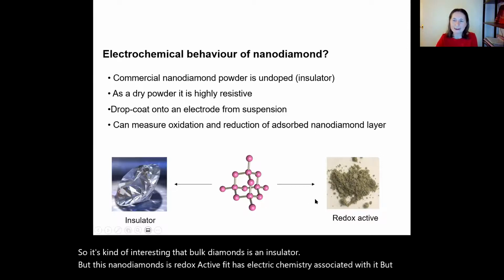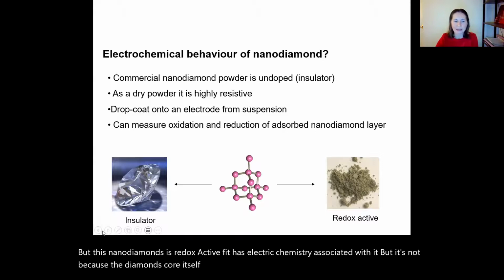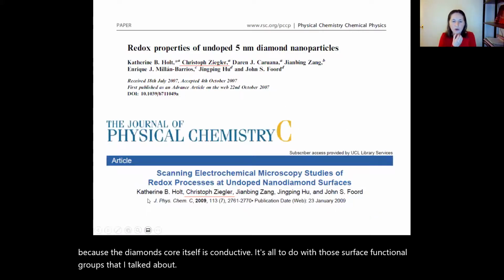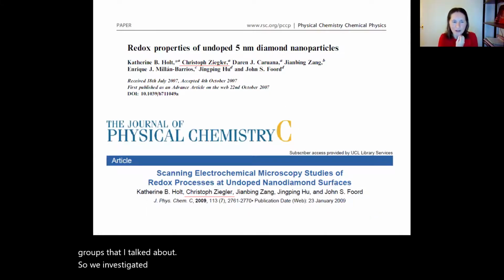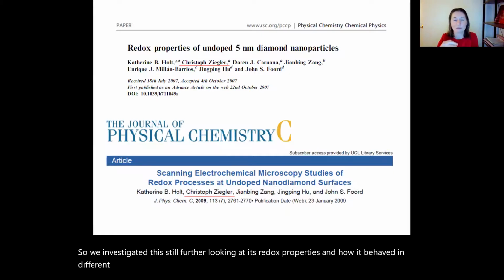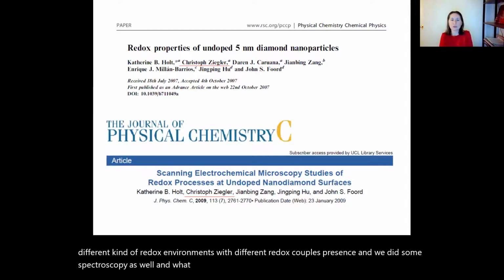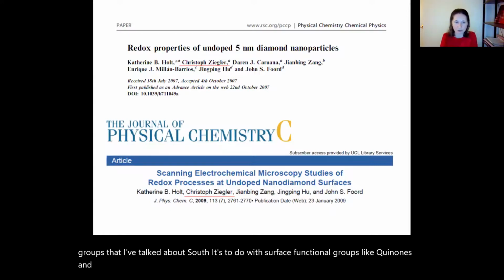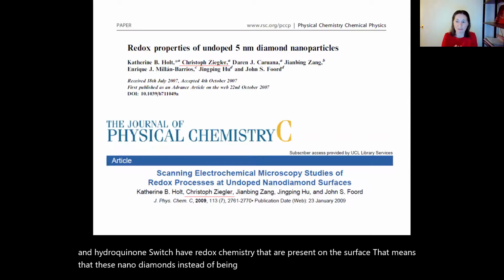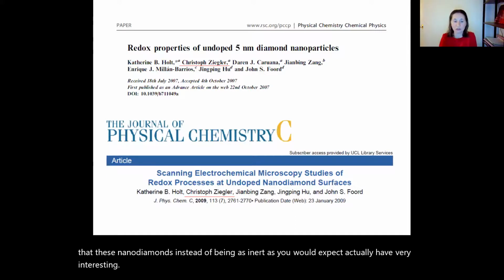But it's not because the diamond's core itself is conductive. It's all to do with those surface functional groups that I talked about. So we investigated this still further, looking at its redox properties and how it behaved in different redox environments with different redox couples present. And we did some spectroscopy as well. And what we discovered was that it's to do with the surface functional groups, like quinones and hydroquinones, which have redox chemistry and are present on the surface. That means that these nano diamonds, instead of being as inert as you would expect, actually have very interesting and rich surface chemistry, including electrochemistry.